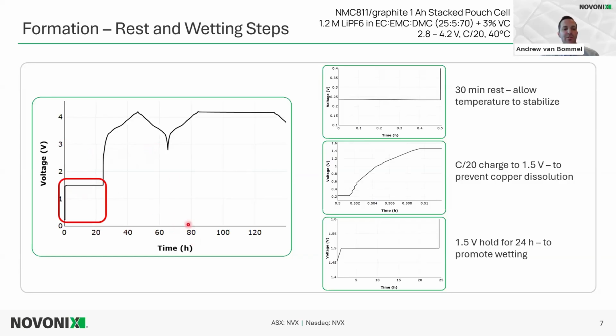Here's the voltage profile versus time for that formation step. First, we do a 30-minute rest. This allows temperature to stabilize. Our standard formation is at a little bit of an elevated temperature at 40 degrees. And then there's a slow or low rate charge up to 1.5 volts. This might not necessarily be required, but it's just to completely ensure that there's no copper dissolution while this wetting step is happening. This wetting step really is just time and temperature, allowing for more electrolyte to penetrate all the pores of the electrodes prior to doing the first charge. So this step and the temperature allows that cell to promote wetting in the cell.